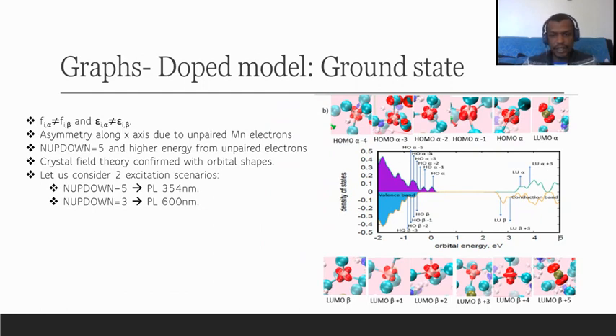So for the doped model at the ground state, we can see that this symmetry is not present. So we have these 5 electrons contributed from the manganese, which are having a higher energy. This is represented by the last 3 peaks in the alpha valence band, which are not symmetrical, and the 2 extra ones that are having higher energy. And here we also confirmed the orbitals by looking at HOMO alpha minus 4 until HOMO alpha to confirm the orbitals that were expected from the manganese ion electrons in the d orbitals.